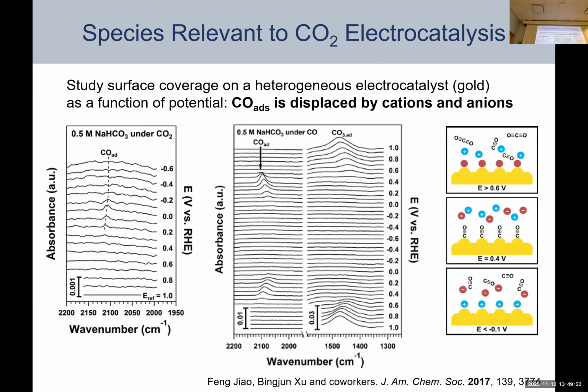And lastly, I wanted to share with you what I think is a really nice study by Feng Jiao and Bingjun Xu in the context of CO2 reduction. So this is a gold electrode that they're looking at for CO2 reduction to make carbon monoxide. And of course, carbon monoxide has a beautiful IR signal. You can see this here showing around 2100 wave numbers. This is adsorbed CO. Okay, but interestingly, if you apply really positive potentials, you see no CO, and if you apply really negative potentials, you also see no CO. So it's just in this tiny little region of applied potential where you can actually record a signal.